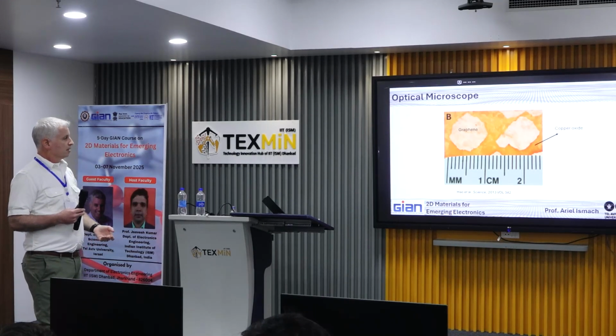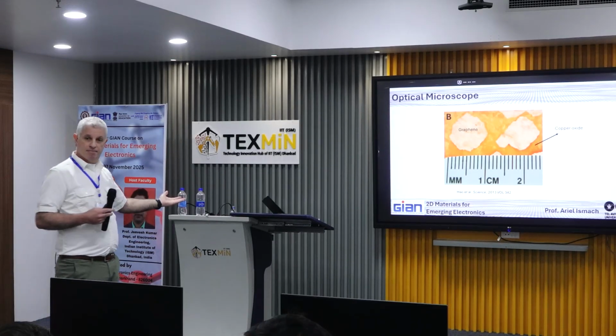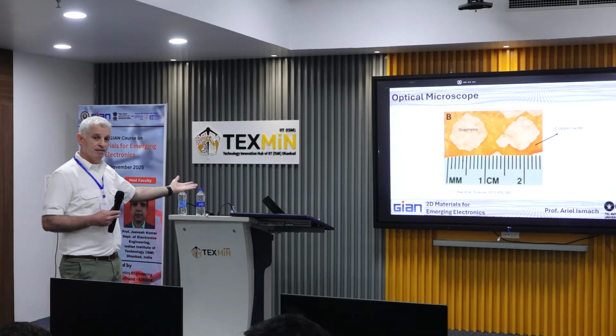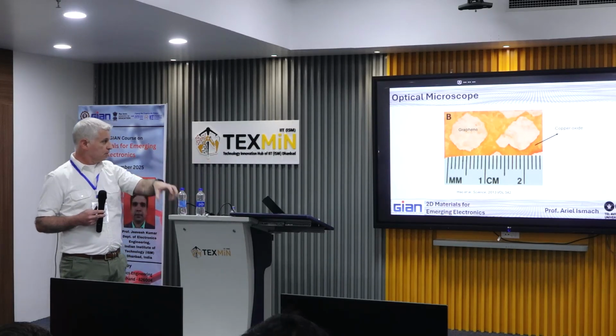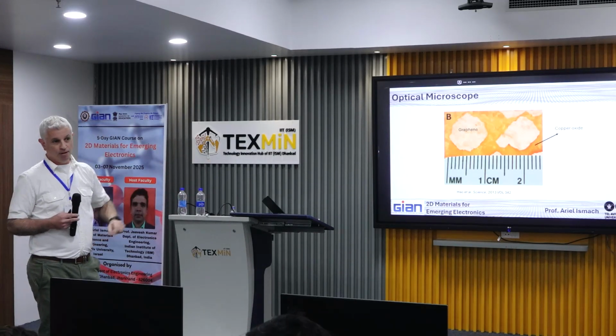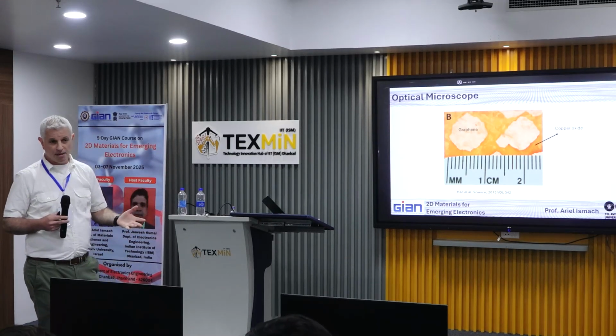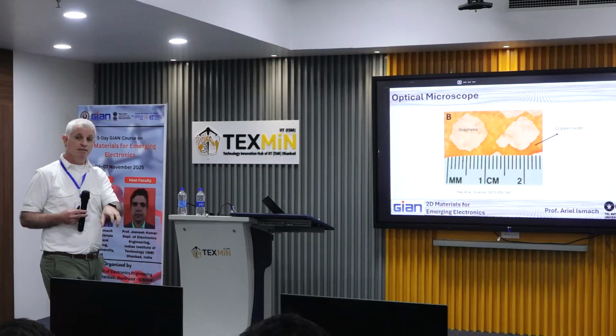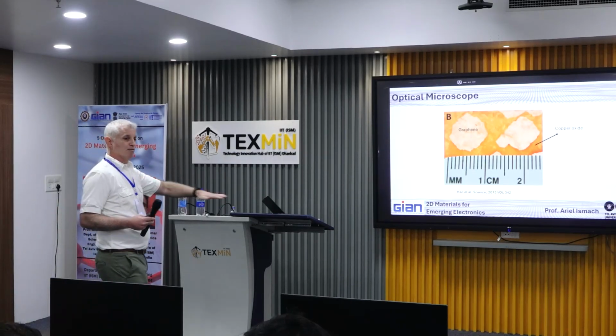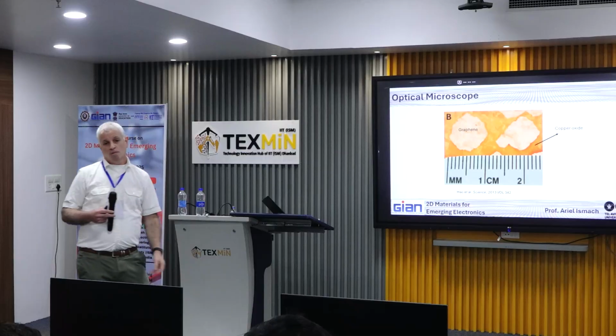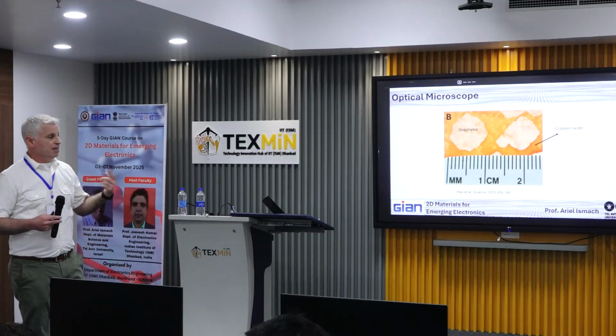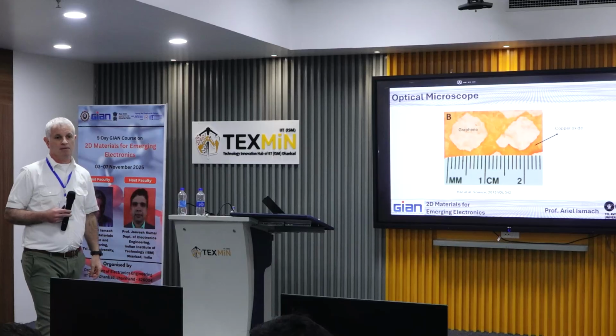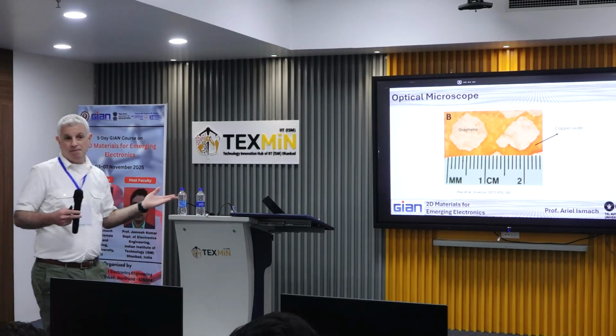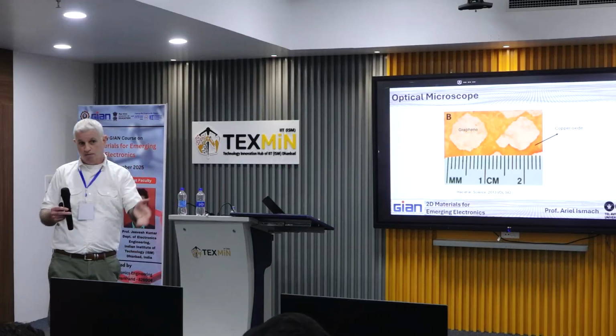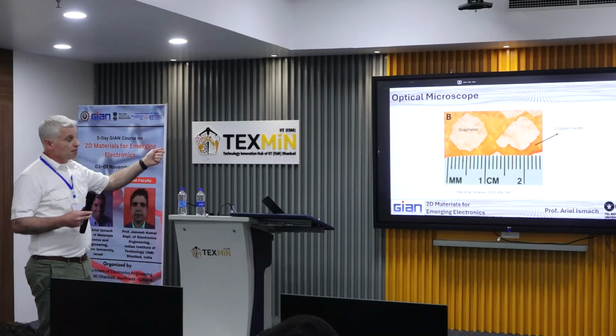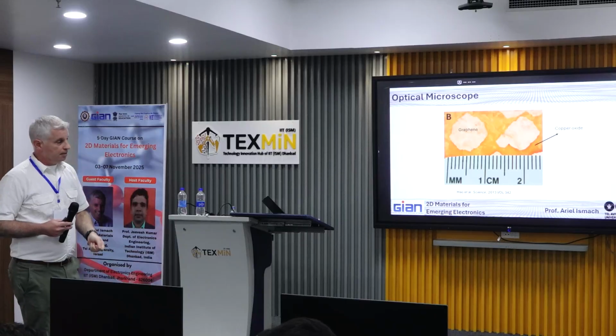You can check if you have, for example, a full layer. If you synthesize a full layer of graphene and you still see spots of oxidized copper, that means, for example, that you have defective graphene. If you have a perfect, high quality graphene, the copper will oxidize much slower. So this is another example. You don't need to go to the SEM. You should go also to the SEM, but this is something that you can get right after the growth.